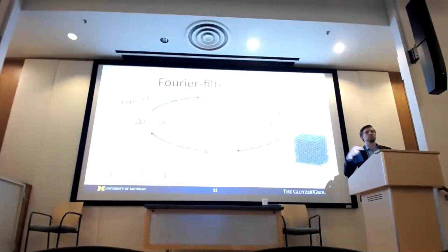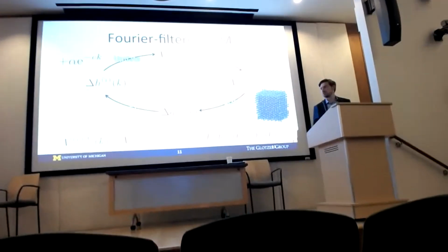Like in the Boltzmann inversion, we start with some kind of function here, v of I, and then we invert it into real space to get something that we can evaluate the forces of. We'll assemble some kind of structure or not, and then we measure the density distribution in K space and apply an update to our potential to better match, or to drive it towards, the desired density distribution.